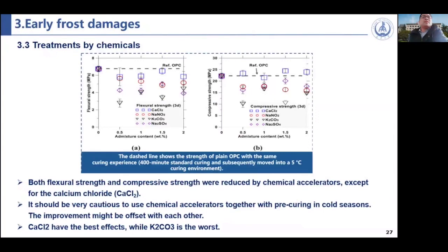So we can conclude from this result that it should be very cautious to use chemical accelerators together with pre-curing in cold regions, because in cold seasons, the improvements might offset each other, or unclear strength development will appear.